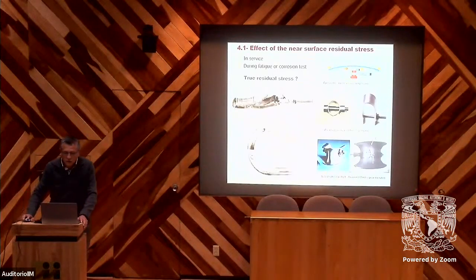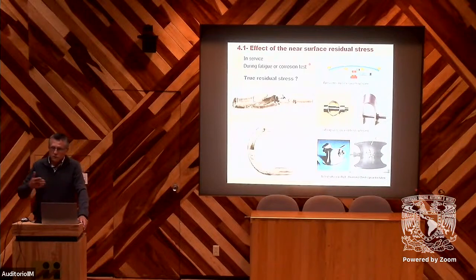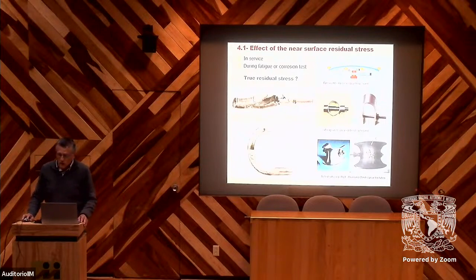And now, this is for fatigue, and for stress corrosion cracking, we can see the same conclusion. We know the effect of residual stresses, the effect of the tension, and the effect of the compression. So the problem is when we make some tests for corrosion, we use many shapes of specimen. We can use tensile, of course, or bending. We can use U-bends to analyze the external skin of the tube, and to study the internal face, we need to use the reverse U-bend.